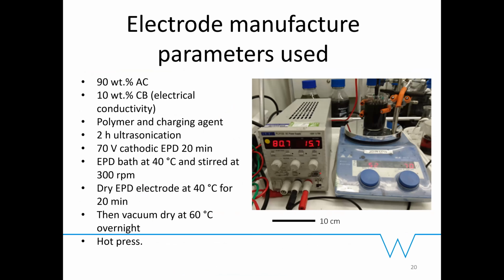There is always a limit depending upon the colloidal quality of the colloids formed in the solution. If it's not possible to maintain the activated carbon suspended in the electrolyte properly, then the thickness will start dropping with time, and it usually does happen. Although in some literature they do mention infinite thickness is possible. Obviously, that's theoretical calculations, with EPD. But in practical cases, it's not. There's always a limitation. And when you start getting very thick layers, you also have problems with the porosity, tortuosity, and excess of electrolyte within the pores and so on. So there are a lot of factors that play a major part.